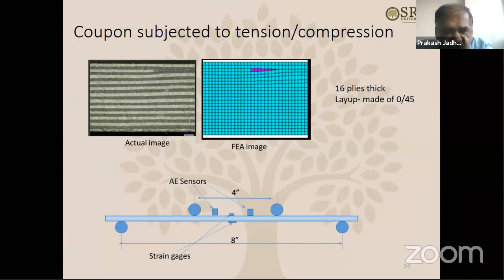Is there any technology available for that? What we did is we tried to use an acoustic emission sensor. Some of you might be aware of it. It actually measures the smallest amount of noise, or sound, that is created in the coupon. Wherever cracks are getting initiated, they may create very, very small noises or sound, and these sensors are very sensitive, so they pick up all those sound events. This is a time-bound test, so let's say it goes on for 20 minutes. Over all the 20 minutes, you can see the sound events.